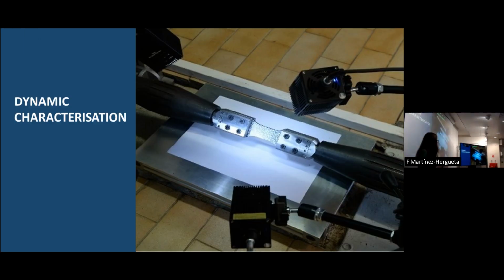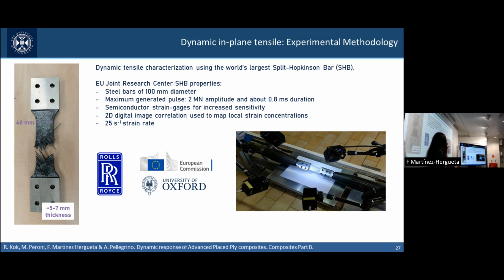So now going through the dynamic characterization, this is definitely the novelty that was not investigated before. Composites that have defects might have a detrimental response on impact. These defects might become more evident when they are subjected to high strain rates, and definitely an undulation can be considered a defect. So we wanted to investigate whether high strain rates might be detrimental for these laminates, but the issue is what I mentioned before. In order to be sure we are really characterizing the response of the parent laminate, we need to go for very, very large specimens.